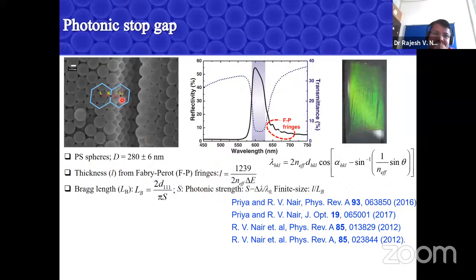This is one image of the sample, taken with a scanning electron microscope. I intentionally show this picture rather than a very nice SEM picture, because you see there are cracks, there's a gap, and there is a missing sphere here. There are dislocations here, and maybe one layer is missing from here. These kinds of things happen in real samples, and one has to avoid all these things. That is another reason why in nanophotonics, even though theoretically it has advanced a lot, even at the single quantum limit, experimentally the field is still very challenging because of the fabrication of the samples.